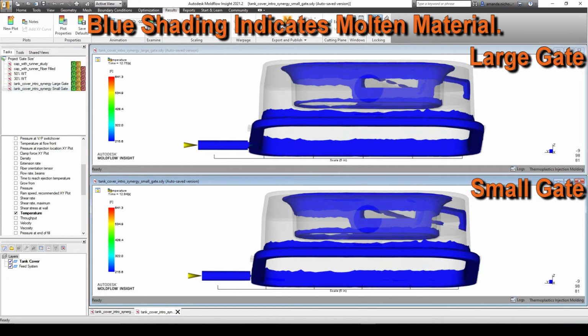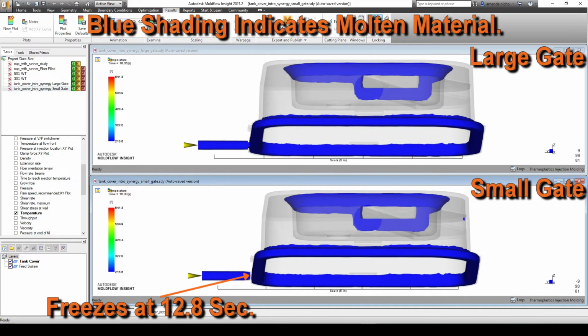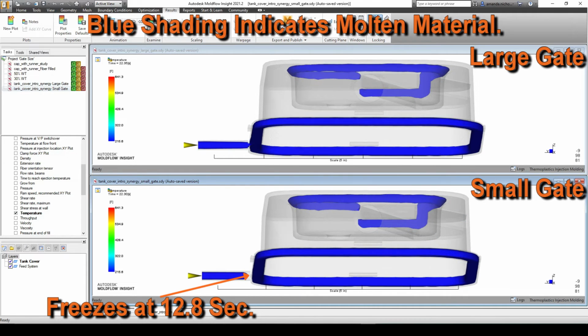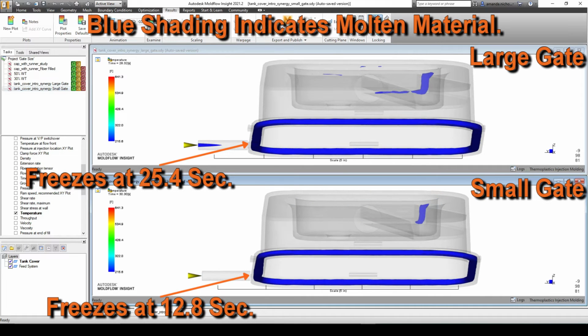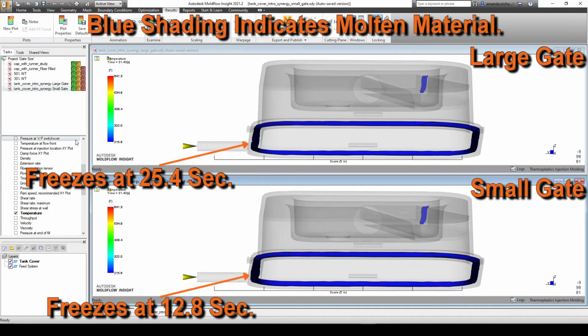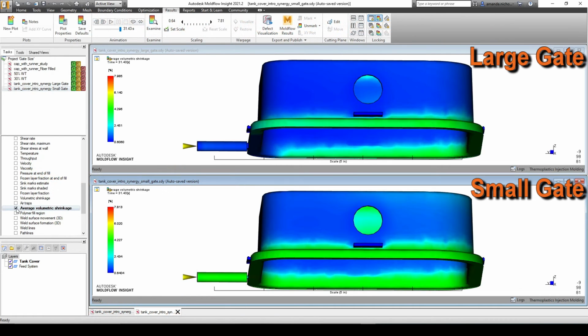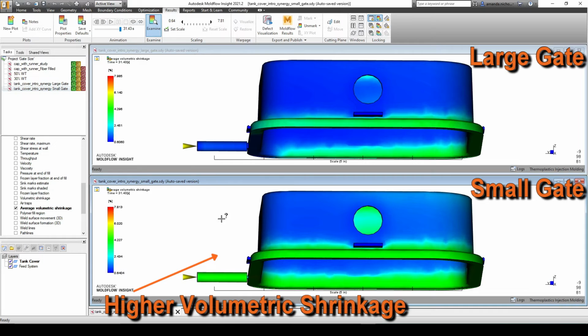If sufficient pack pressure cannot be maintained on the molten polymer as it cools, the results are weaker parts with sink marks, voids, warpage, and reduced impact resistance. Therefore, the gate needs to remain molten long enough for pack pressure to compensate for volumetric shrinkage of the part. Larger gates will allow for longer packing times, which may allow for more flexibility in the packing pressure profile.